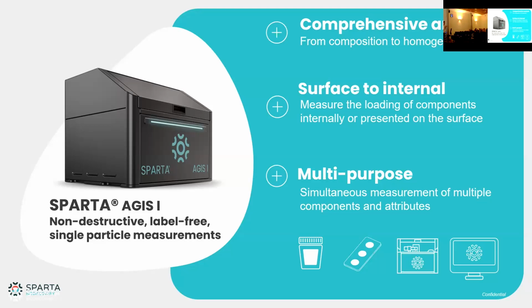So when we look at the Raman signal, the raw signal that comes out, we can look at this in a non-normalized way, so basically raw signal intensity, and the variation there is indicative of the size of the particle. What we tend to do is take the really big peak you saw in the middle, which is a carbon-hydrogen vibration, which is everywhere in your particle. So that's indicative of the size of the particle. Looking at non-normalized spectra, the raw intensity changes, we can see how variable it is between particles, and that's quite accurate.